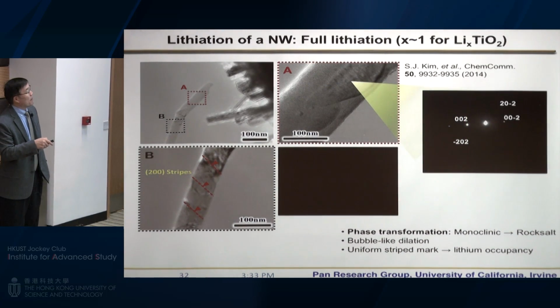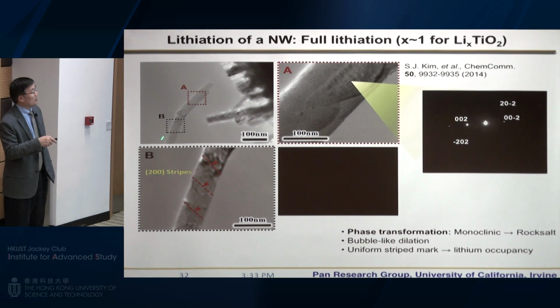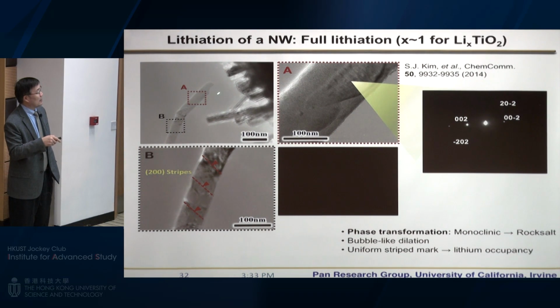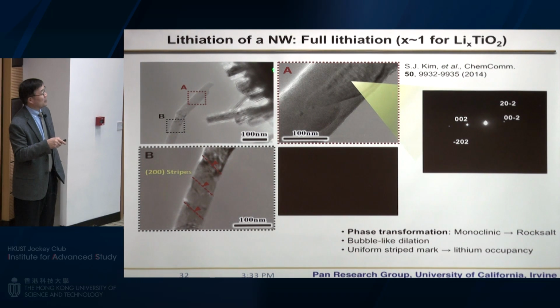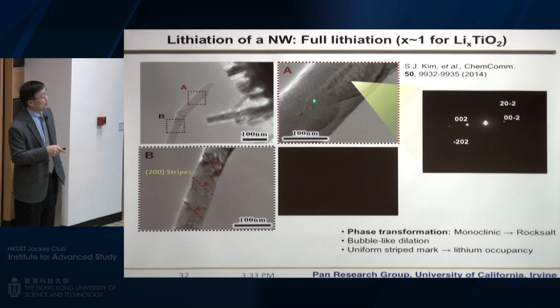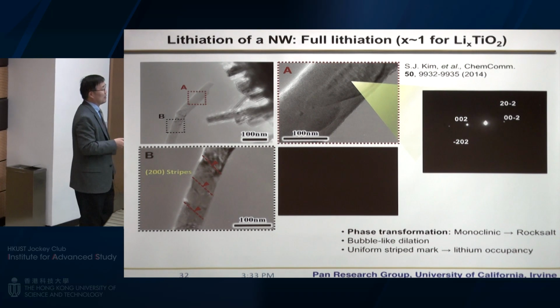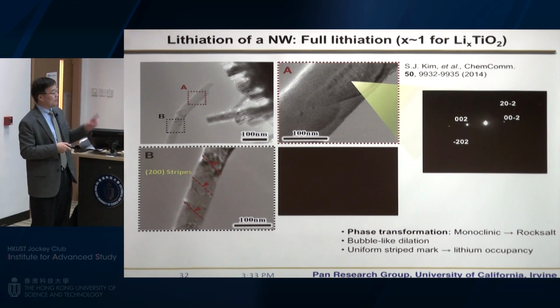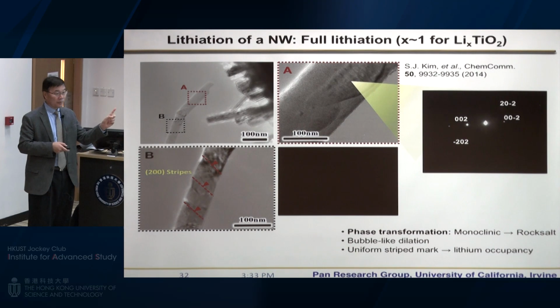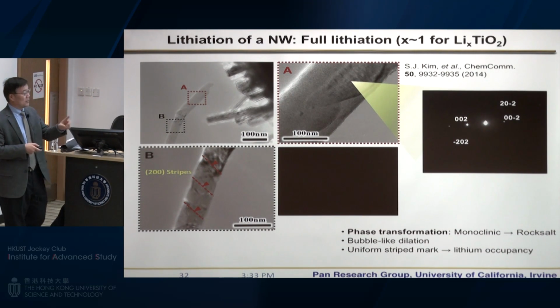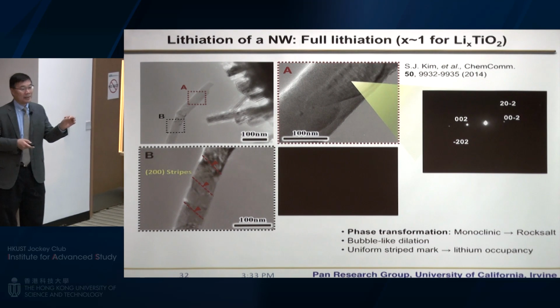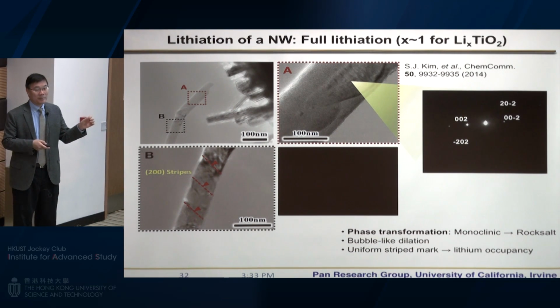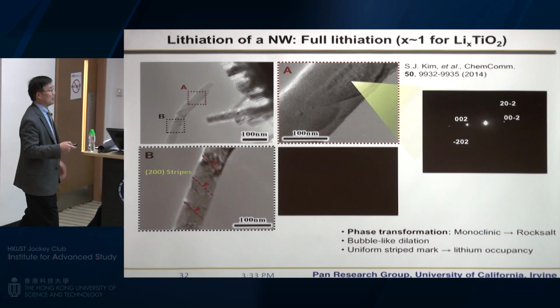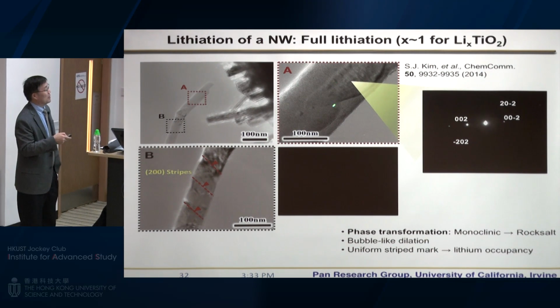All right. So if you let lithium diffuse further, then the monoclinic phase will change to another phase, rock-salt. Okay? Rock-salt has more lithium inside. But the previous transition, from rutile to monoclinic, is reversible. For the monoclinic to rock-salt transition, according to TEM study, it's very hard to be reversible because the structure just changed too much and a lot of defects were introduced.